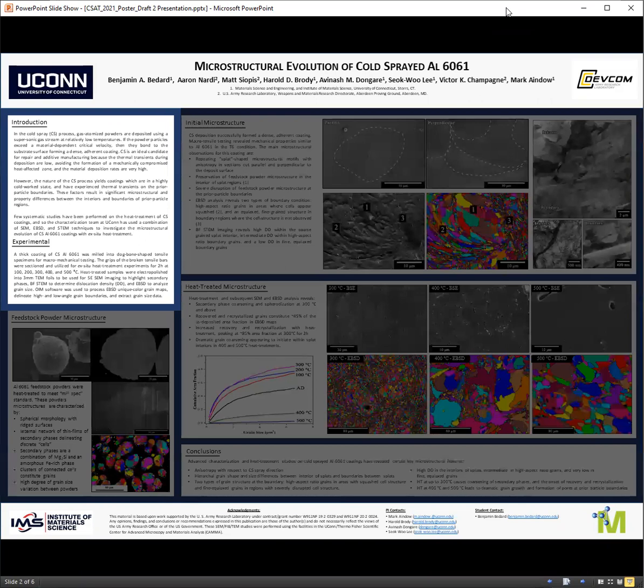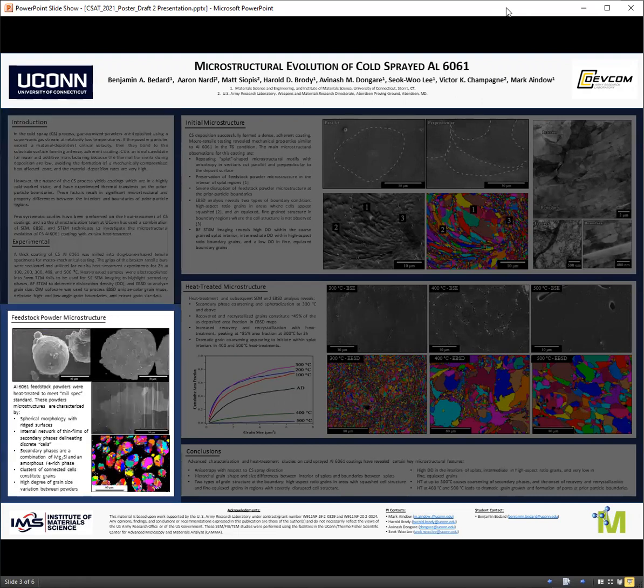For the experimental procedure, thick aluminum 6061 coatings were sectioned into heat treatment specimens and subjected to heat treatments between 100 and 500 degrees Celsius for 2 hours apiece. Once treated, the specimens were thinned and twin jet electropolished into 3mm TEM foils to be used in SEM, EBSD, and STEM imaging. The aluminum 6061 powders used to build these coatings were processed to meet the mil spec standard.